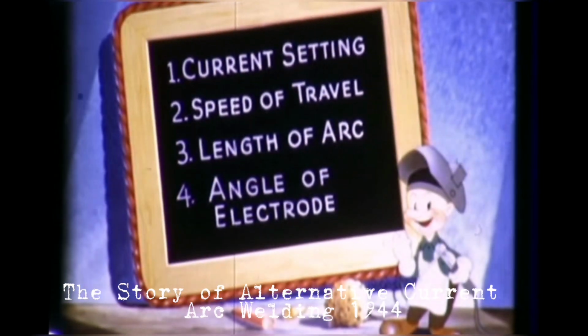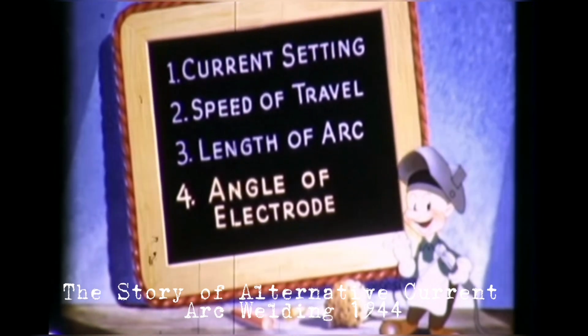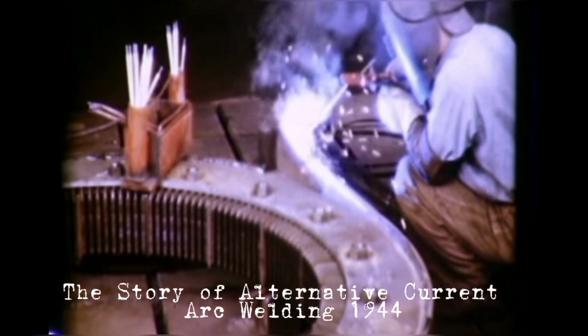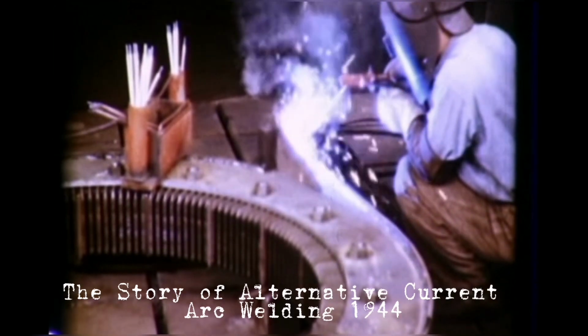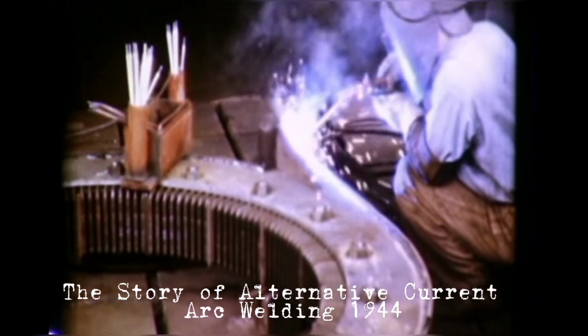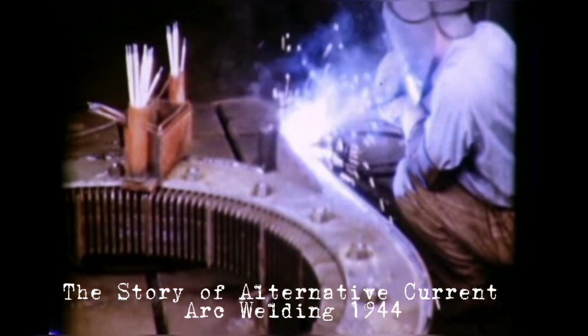And now, the fourth factor, angle of electrode. It is in this respect that AC welding contributes the most in simplifying welding technique. In welding with direct current, it is often necessary to manipulate the electrode in an effort to overcome the effect of arc blow. When arc blow is severe, as when welding in a corner, the resulting weld is irregular. Spatter and undercutting are excessive. A cross-section shows poor fusion and severe undercutting.